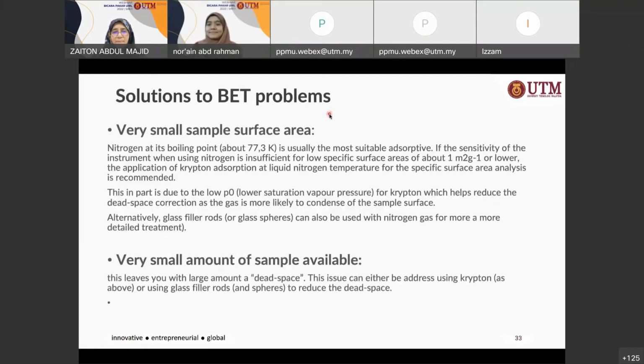And solutions to some of the BET problems, yeah? If you have a very small sample surface area, your nitrogen adsorbate might not be suitable. You might change to another adsorbate. Krypton is actually quite suitable for small surface area samples. For example, maybe your filler rods or the glass spheres are not suitable. Yeah, you might want to change that. Okay. Or you can have a very small amount of sample available. Yeah, so maybe this leaves you a very large dead space. So this can be addressed by using maybe filler rods or spheres to reduce the dead space in your sample.